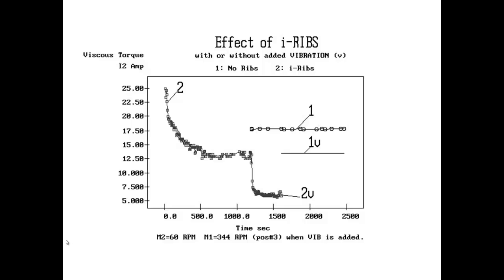Okay, here in this slide we show the effect of the design of the intelligent ribs, and the fact that it is equivalent to adding an external vibration is demonstrated in this slide. So we have a viscous torque as measured by the amperage, the intensity of a current to turn the inner cone with a given melt at a given temperature, flowing with a given flow rate from the extruder, a given feed.